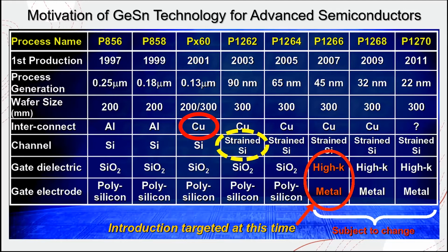So strained silicon and copper interconnect and high-k material in combination with the metal gate have been found in Intel. So the motivation of germanium-tin technology can be found in the strained silicon. So by introducing germanium into silicon, we can expect a better, higher hole mobility. And if there's a tensile strain imposed on silicon by the incorporated germanium, we can also expect enhanced electron mobilities. So what germanium did in silicon can be expected from tin.